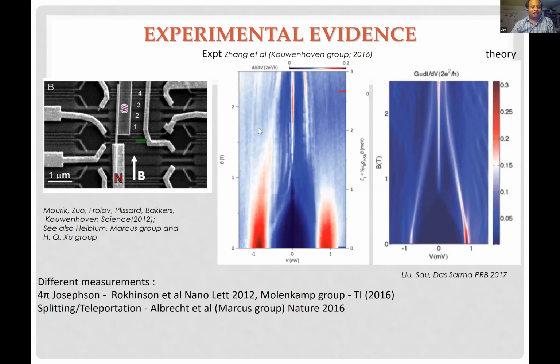The good news is that 2 years after we made the prediction, some part of this was seen in a few experiments. I'm only showing one of the data sets. The experiment is an indium antimonide wire covered with superconductor, and we're tunneling from the normal lead to the superconductor through the end Majorana, applying a magnetic field along the wire. We see that above a certain magnetic field, you get a nice zero bias conductance peak in some devices, and you see something like a gap closure.